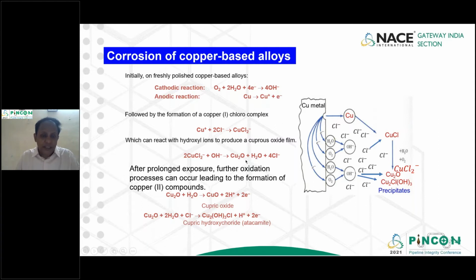So this is very tricky here. The formation of this cuprous oxide, or the transformation of that cuprous to cupric, we only encounter in a metal like copper in a static case. But the moment we go to flow condition, or the erosion-corrosion condition, the formation of copper oxide is limited and doesn't form actually, which we will see in one of our examples.